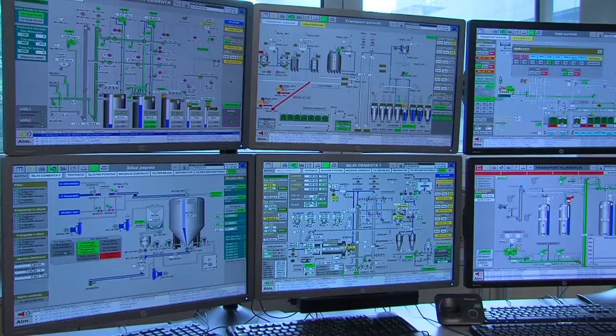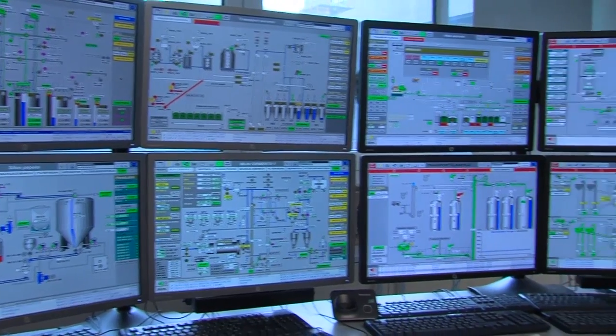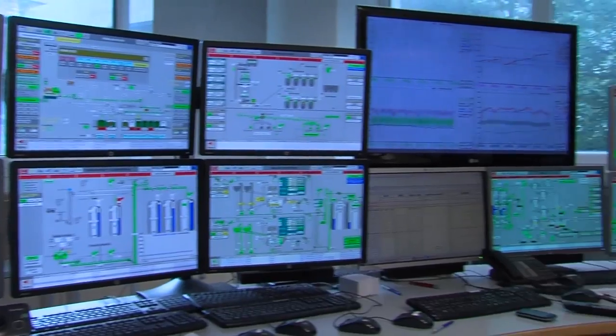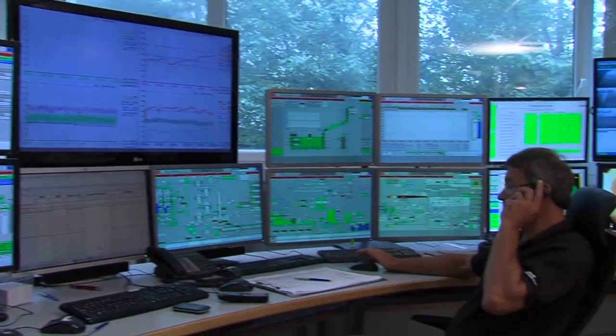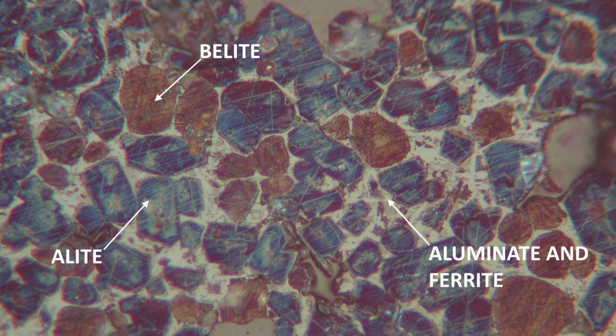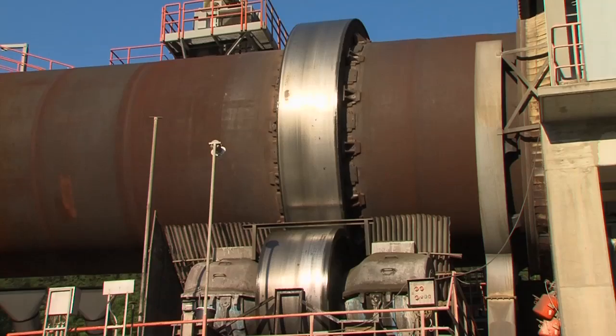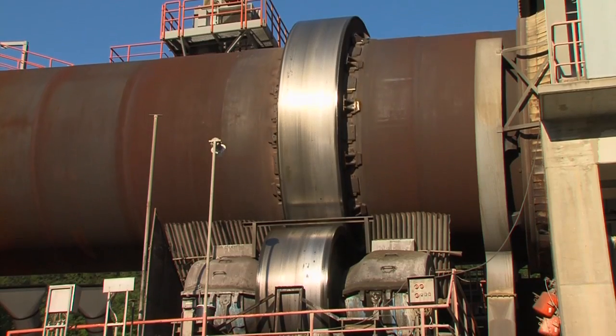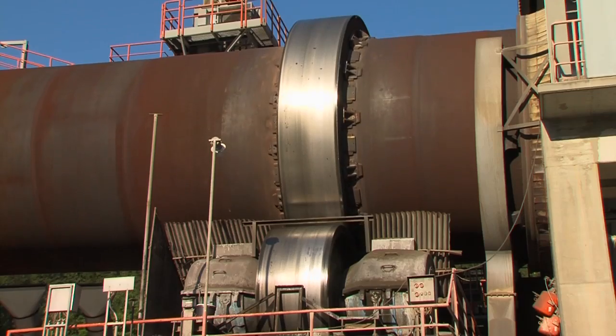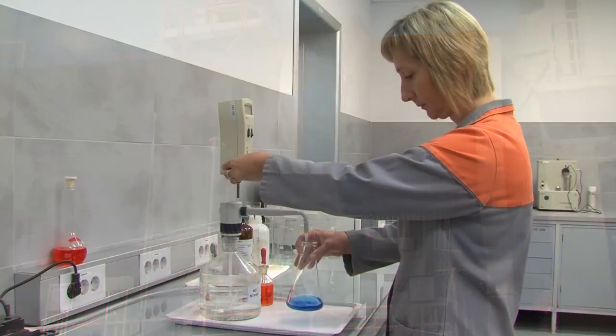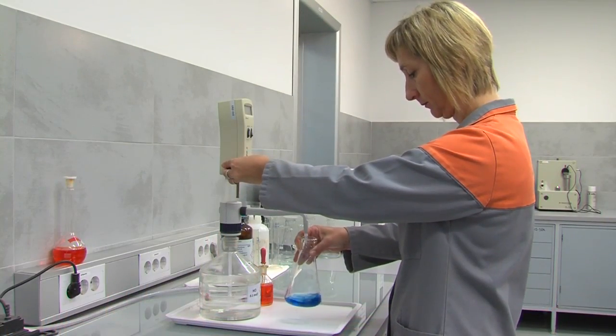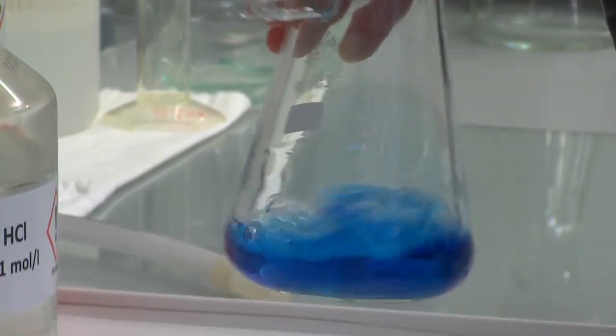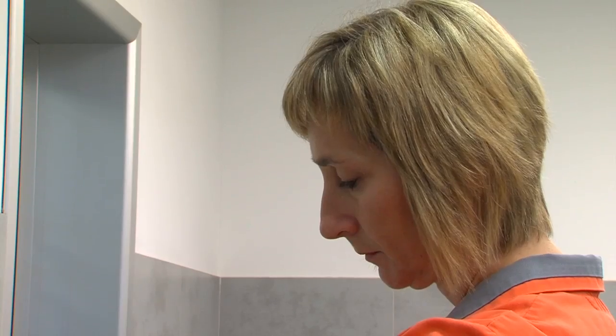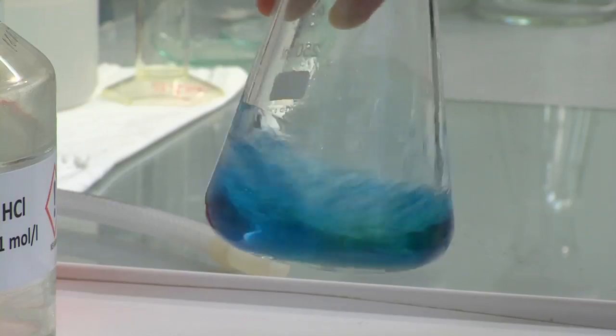During burning, the material is partially melted. This causes complex chemical reactions that led to the formation of clinker minerals: alite, belite, aluminate, and ferrite. In the final phase, the clinker is quickly cooled in a clinker cooler. The content of free lime, which has to be monitored regularly, is one of the criteria for determining the quality of clinker.